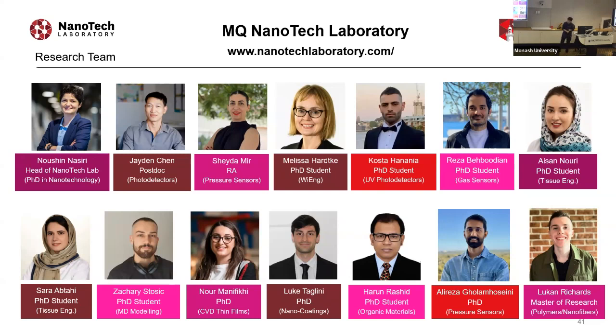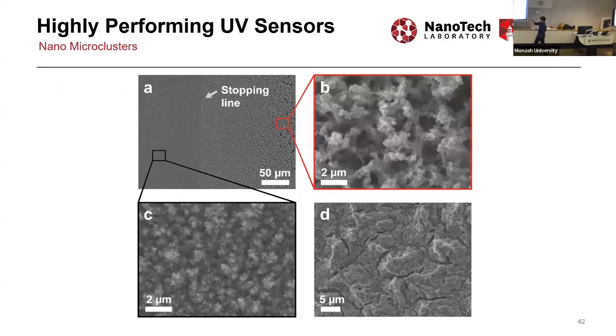We tried DMF, we tried toluene. Toluene worked very well. I would say maybe a different liquid for different structures and also a different liquid for different metal oxides, so we optimize from that perspective. You can also change the evaporation time. If you do it on a heater, you evaporate it much faster, and you would end up with a slightly different structure. Also, with the type of droplet, we've done all the way from 1 microliter, which is the same size as the sensor film, all the way to 10 microliter. Yeah, and look at this one. I think this one is water.